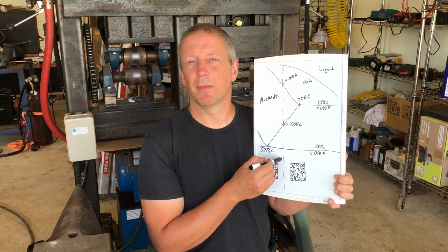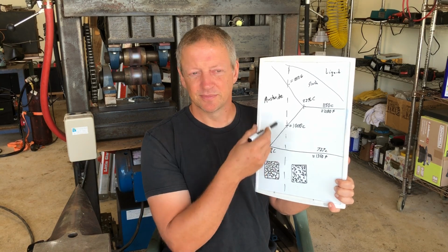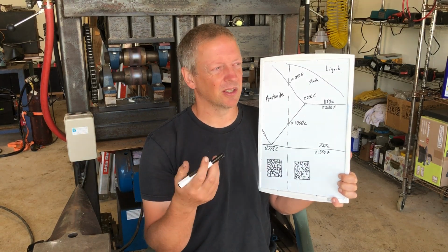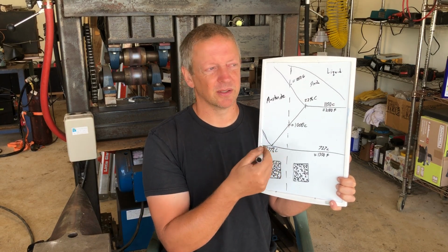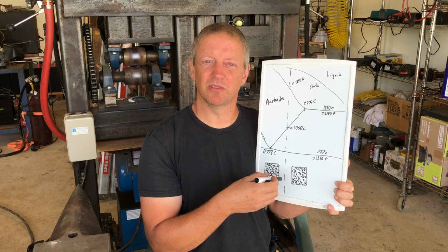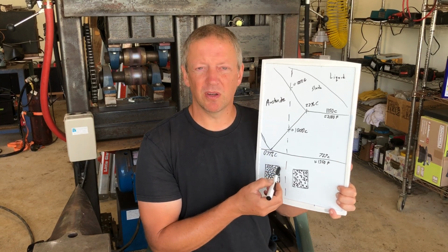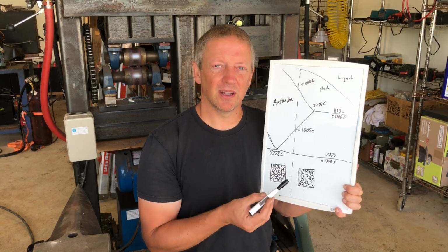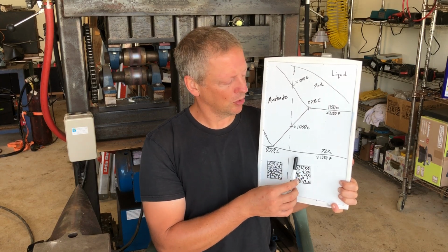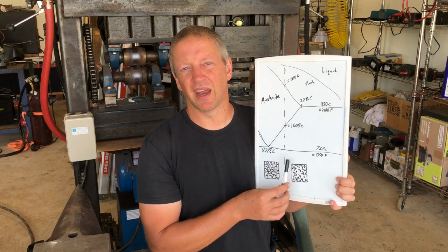Subcritical forging, bad. As things are cooling, it's very easy. When you're forging a blade, whether it's Wootz or otherwise, you're forging your blade and the steel's still moving nicely, and you end up going subcritical with it. Well, I'm going to tell you something. You didn't go subcritical. This line moves based on how quickly you are heating or cooling.